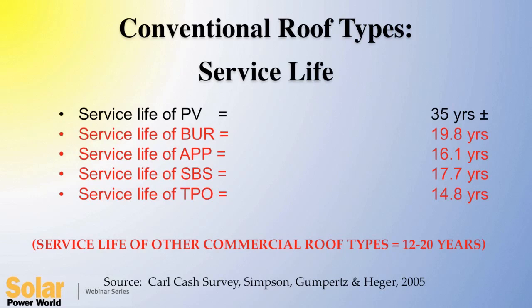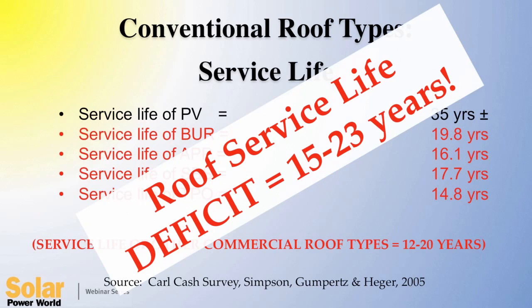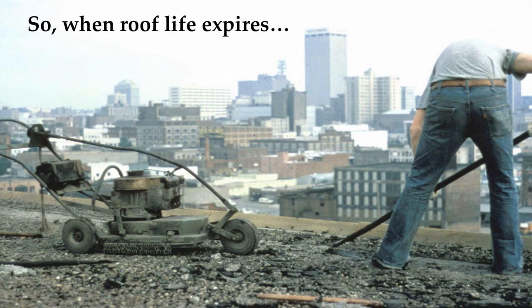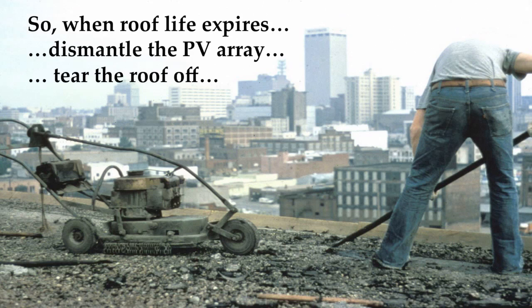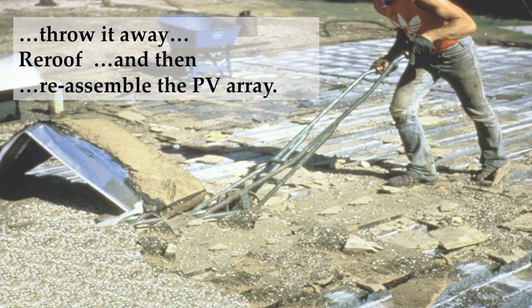Well, if you do the math here, you can see right away that there's a little bit of an issue over here in that column on the right. It amounts to what I call a roof service life deficit. In other words, the roof life is expiring long before the service life of the PV, to the tune of 15 to 23 years, depending upon the roof type. Now, the consequence of that is fairly obvious. When the roof life expires, dismantle the PV array, tear the roof off, throw it away, re-roof, and then reassemble the PV array.